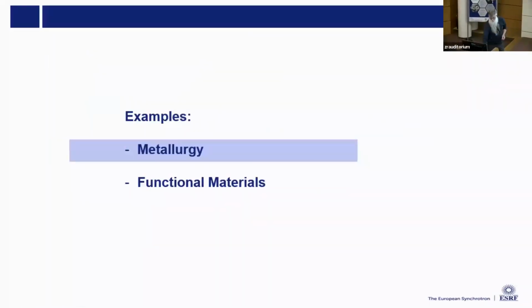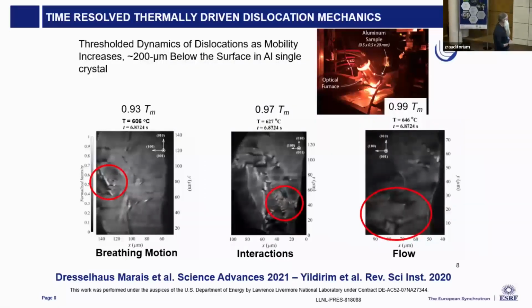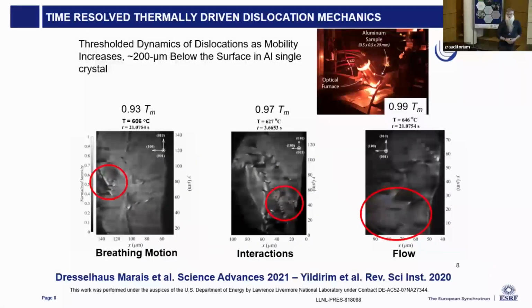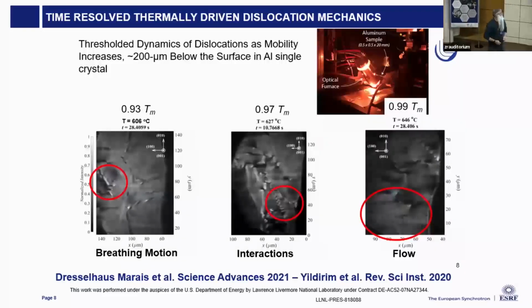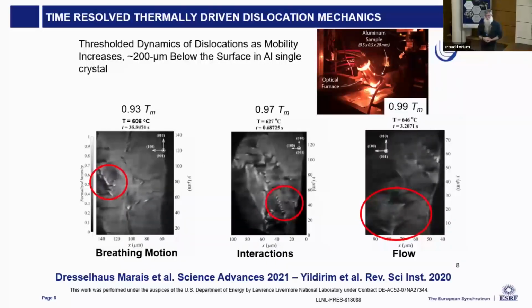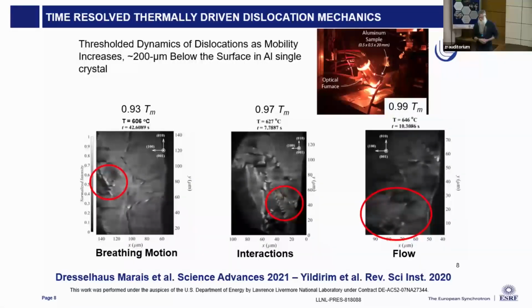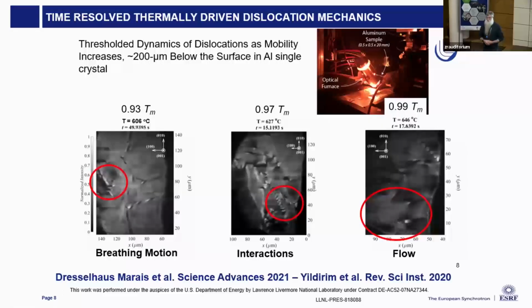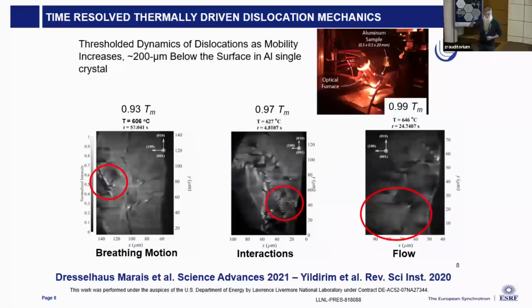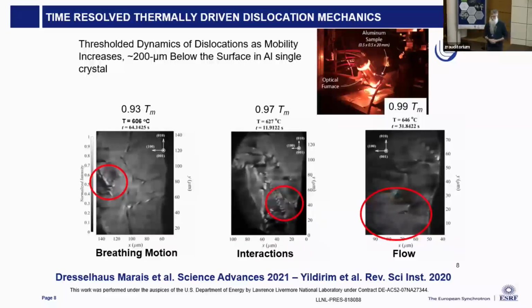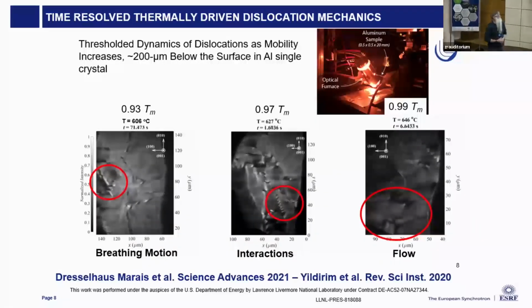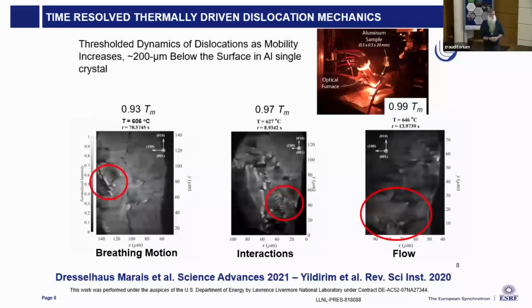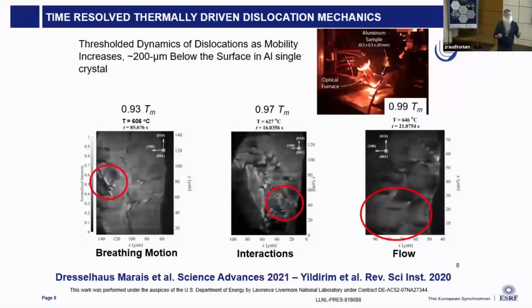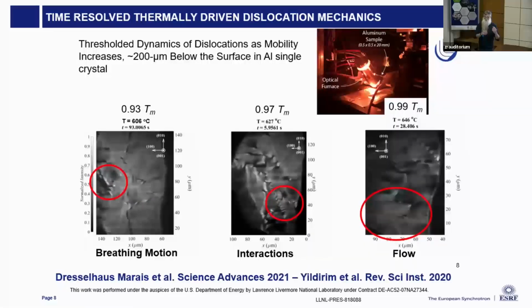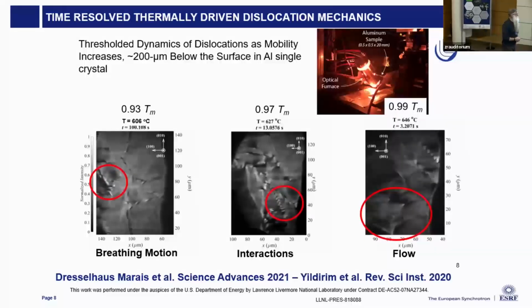So just to give you an example from metallurgy, this is an experiment that was done by Leroy Dresselhaus in collaboration with John Ilgrim, who's somewhere hiding in the back there, didn't come to the front row. We had a single crystal of aluminum that was before the experiment already quite well annealed. So we have a quite small number of dislocations, lattice faults, and then we heat the sample up to very, very close to the melting point. So 93% of the melting temperature, 97 and 99% of the melting temperature. And we can see actually at those temperatures that the dislocations become mobile and they move around the sample. They form structures, they arrange themselves into minimum energy configurations.